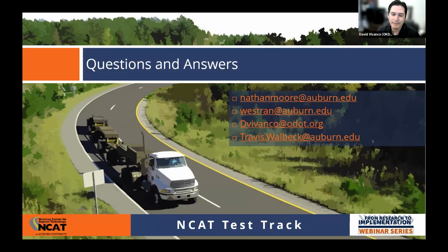So we don't really see that. I mean, that's not the case for most of the DOTs in the real world. So yeah, you want to set your criteria based on your local conditions. We did a benchmarking study to pick that 100 threshold, and that was done for the pilot project specifically. And the idea was to have a sufficient difference between our Superpave mixes and the BMD mixes that we were going to evaluate on those projects.